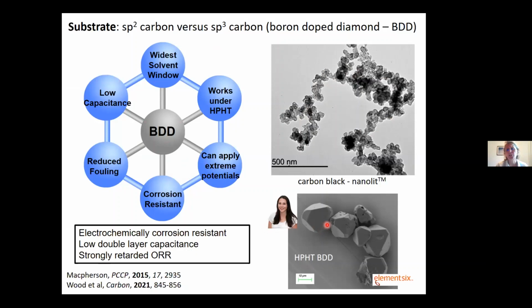We've been basically looking to produce diamond via an alternative, cheaper route, which is high pressure, high temperature. So you produce these kind of microparticles of BDD, which themselves are particulates which behave as almost the CVD material. This material can be milled further. So this is an interesting material because it potentially opens up a route to produce high volume BDD.